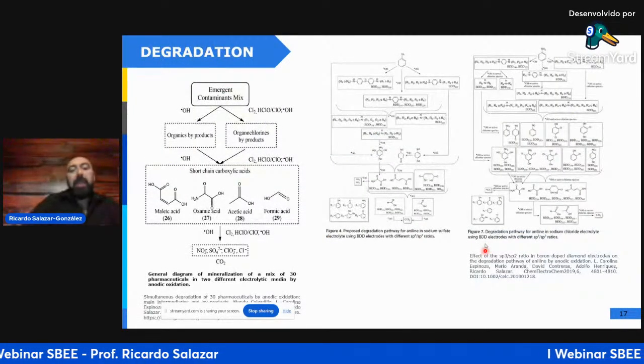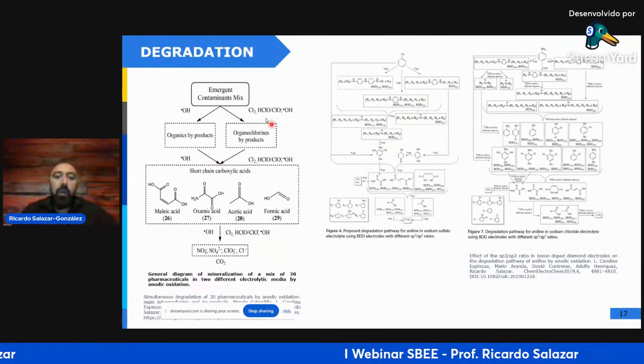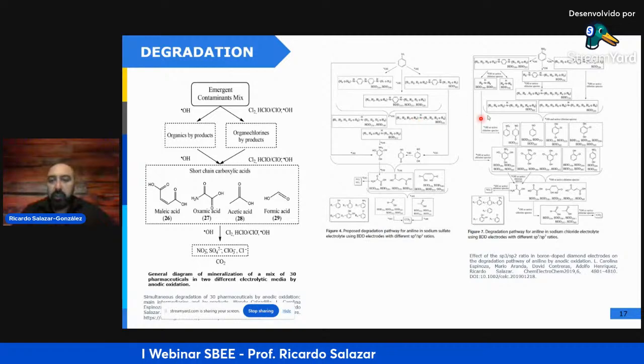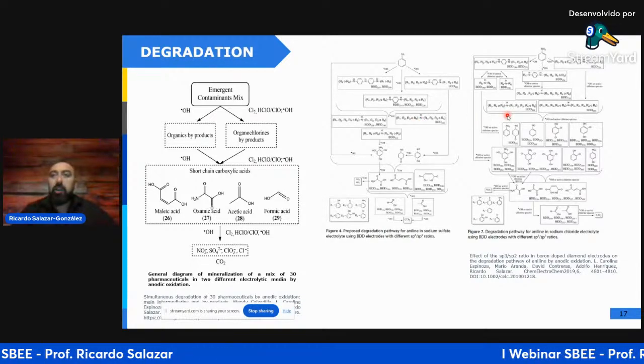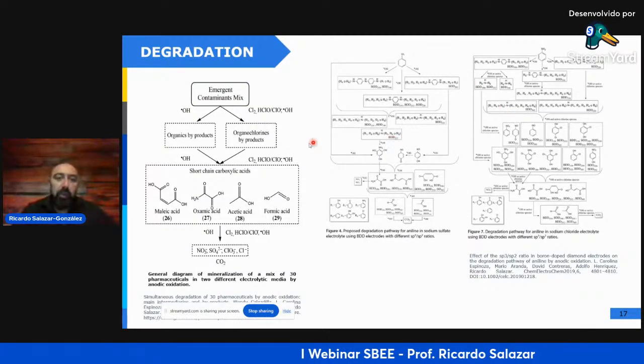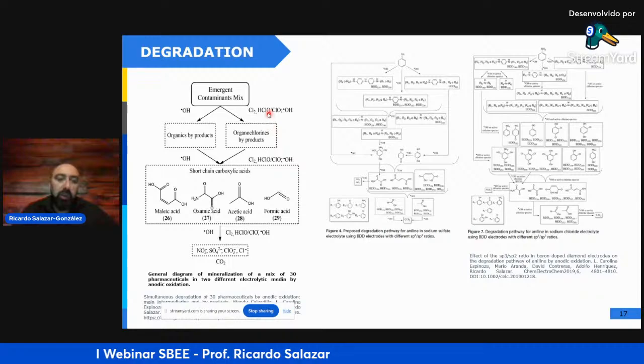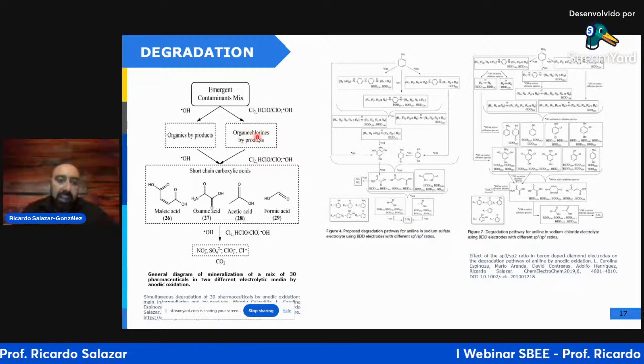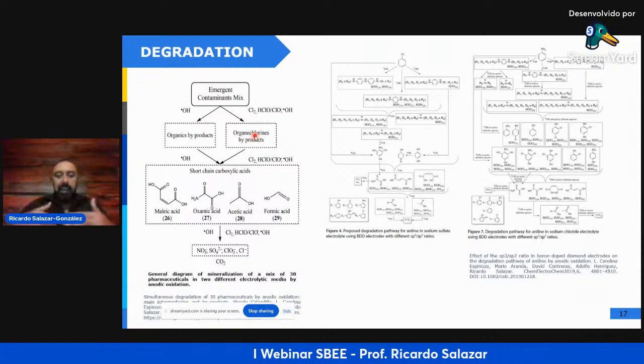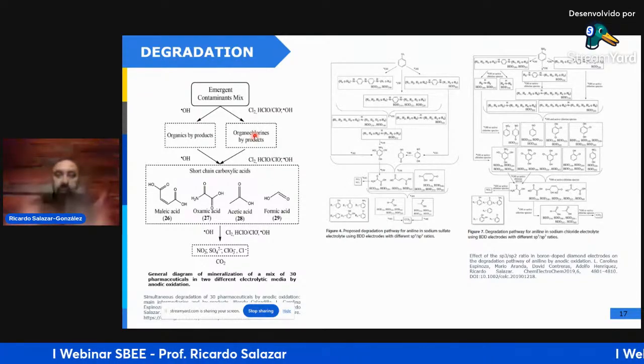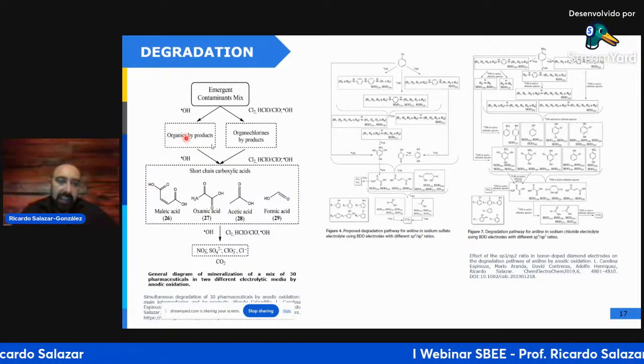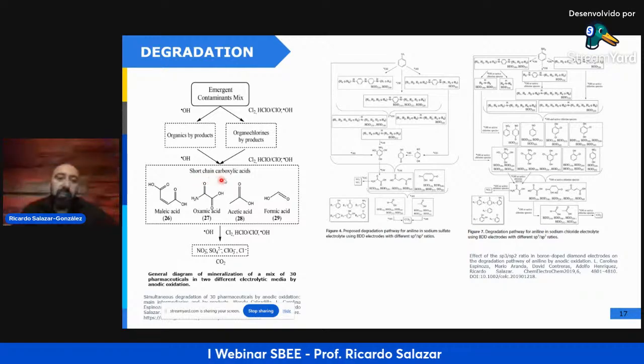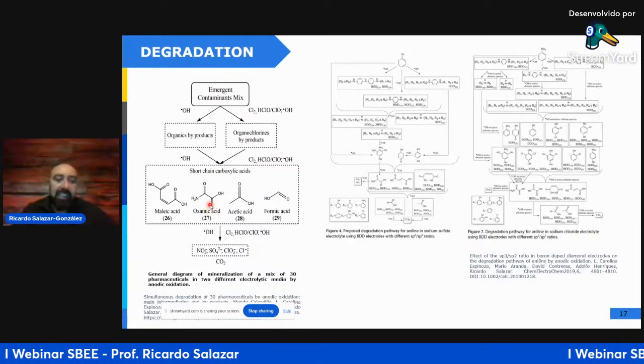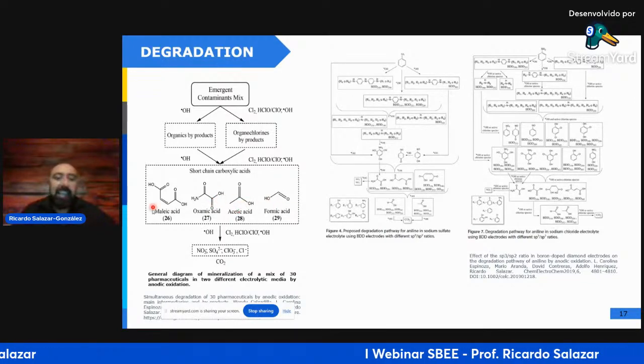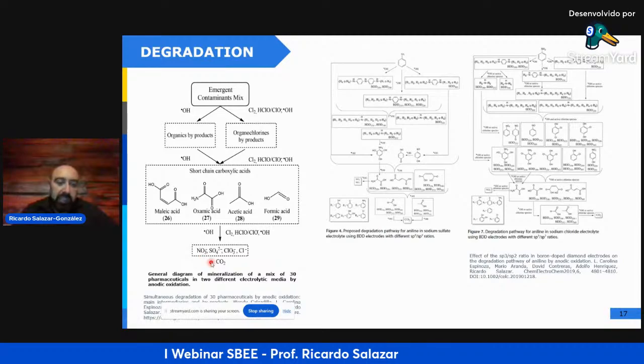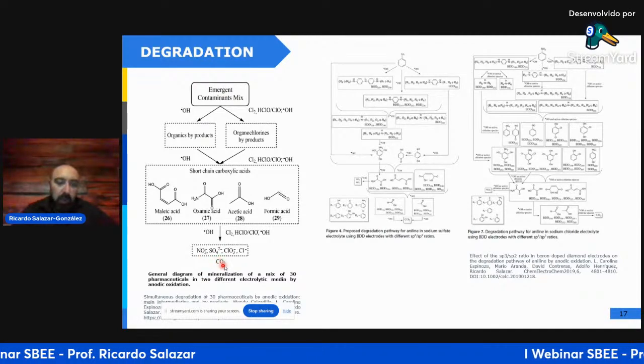And depending on the electrode, we can obtain different mechanisms for the reaction, because the concentration and the kind of oxidant produced on the electrode surface produce different organic byproducts. If we have chloride in the solution, we obtain organochlorine byproducts, but as the electrolysis continues producing oxidants, these hydroxyl radicals react with these organic byproducts, producing short-chain carboxylic acids, mainly oxamic acid, oxalic acid, and formic acid, and these acids react with the hydroxyl radicals, producing the complete transformation of the pollutants to carbon dioxide.